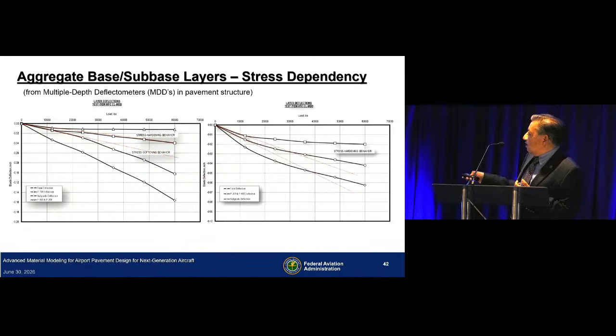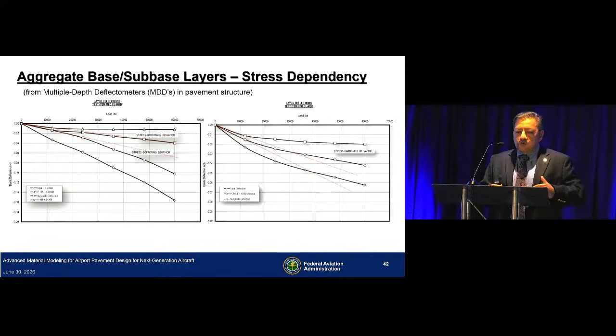What you see on the right side is for high strength subgrade, which was a sandy soil or a granular soil. The subgrade shows stress hardening behavior, and the aggregate layer shows stress hardening behavior. So the total behavior of the pavement structure is also the combination of that. So when you consider linear elastic behavior and you have materials that are showing stress softening and stress hardening, depending on where you are in terms of stress, you could be under-predicting or over-predicting pavement responses, which in turn results in under-prediction or over-prediction of pavement life. And that's what you can relate to what we observed under full-scale testing.